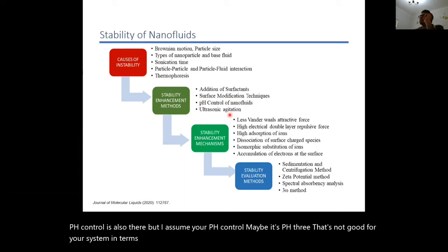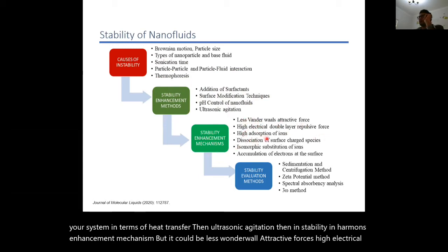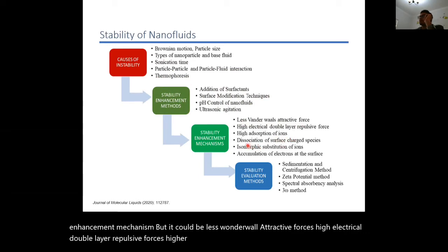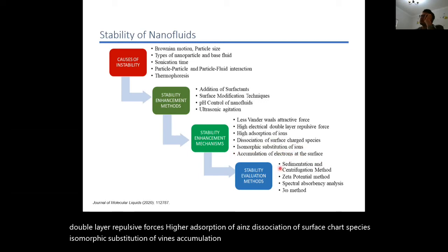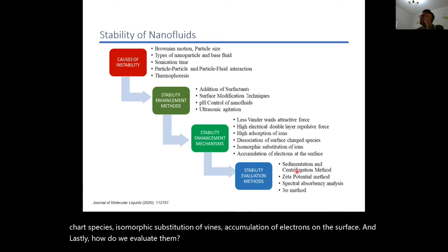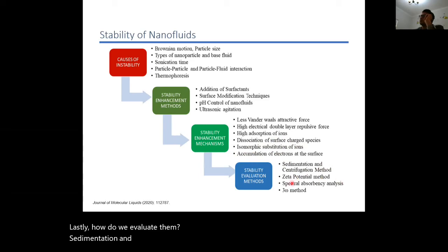Then in stability enhancement mechanism, it could be less van der Waals attractive forces, high electrical double layer repulsive forces, higher adsorption of ions, dissociation of surface charged species, isomorphic substitution of ions, accumulation of electrons on the surface. And lastly, how do we evaluate them? Sedimentation and centrifugation method, zeta potential method, spectral absorbency analysis, and 3 omega method.